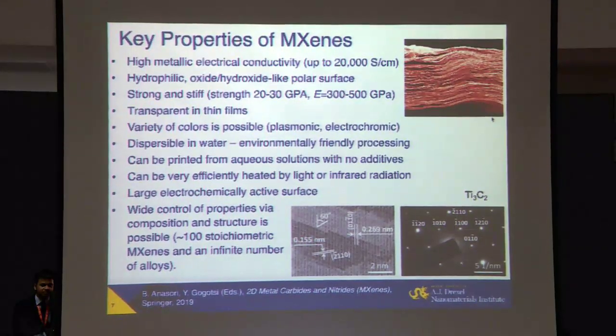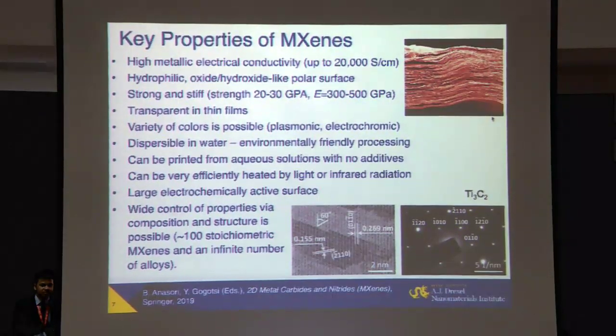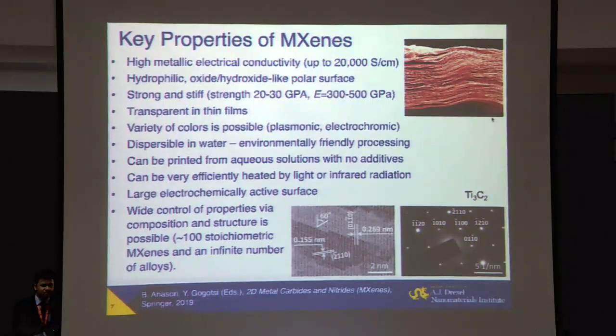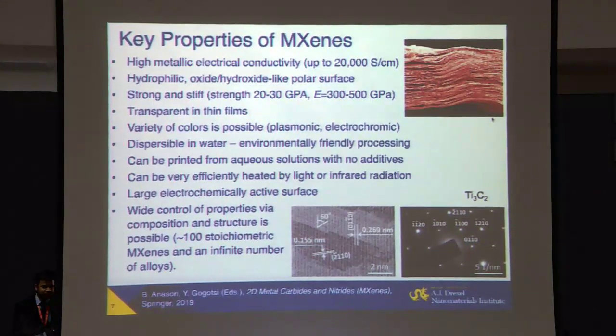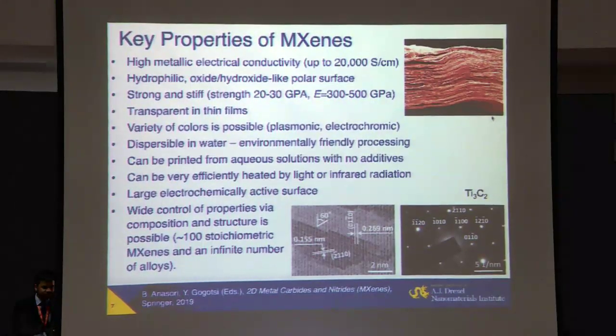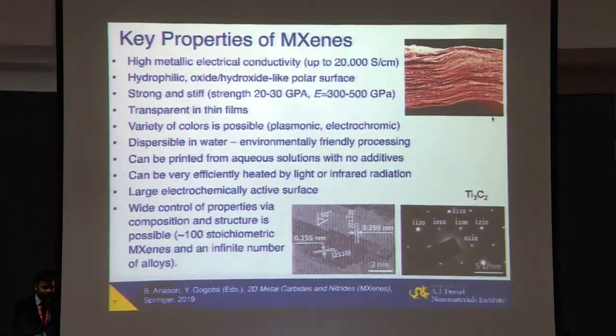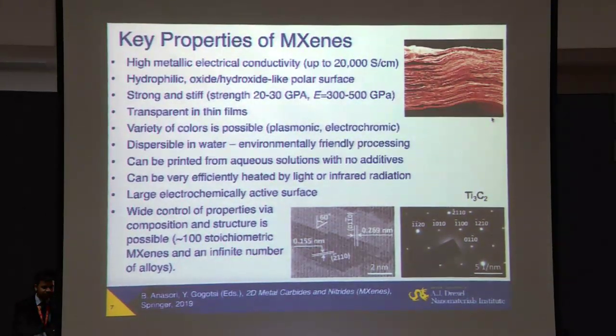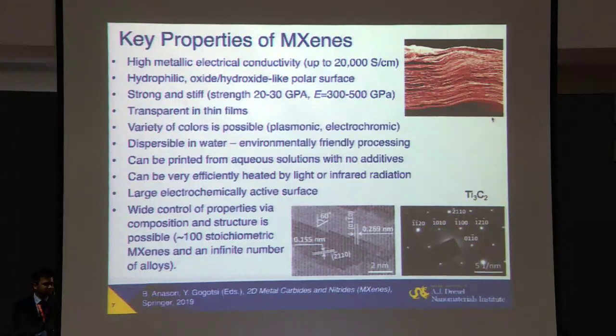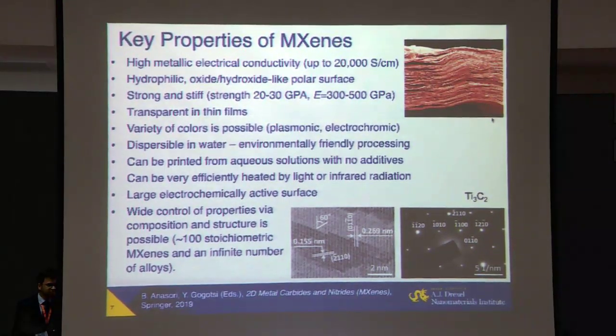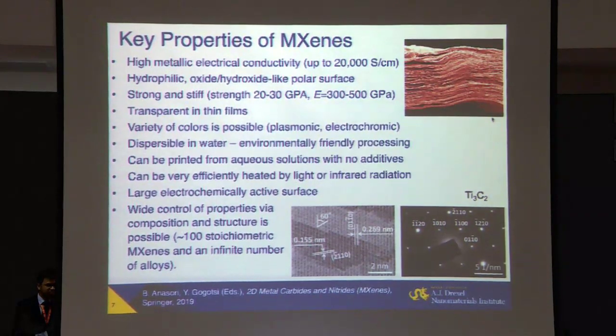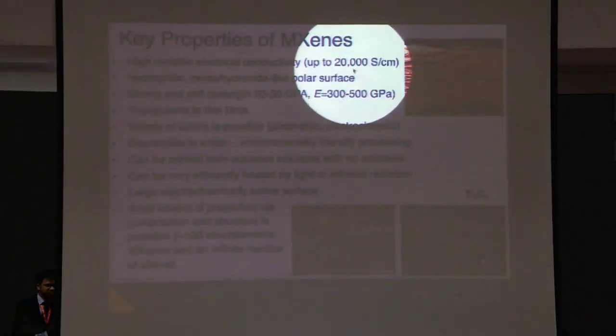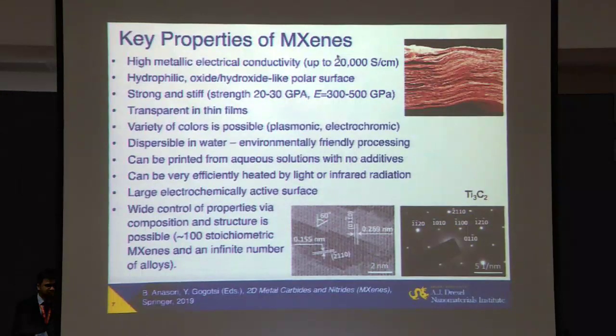Those materials have high density of states at the Fermi level and high concentration of carriers. As a result, if you don't want a monolayer graphene, but make a film out of graphene, what most applications really require, from reducing graphene oxide or mechanically exfoliating graphite, you end up with conductivity of about, say, 2,000 siemens per centimeter. We get up to 20,000 on titanium carbide Ti3C2 MXene right now.